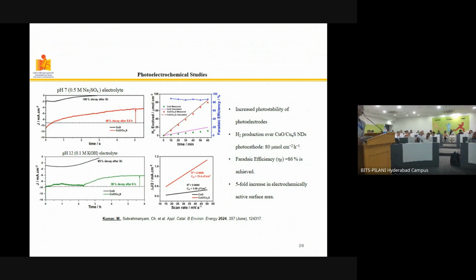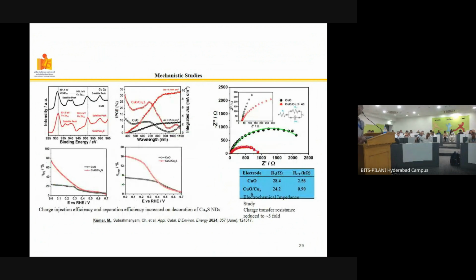And you can also give the hydrogen evolution comparison. You look at the other studies, which also confirm that the Faraday efficiency, if you report, all these things look to be good. Then if you look at the RCT value, the charge transfer resistance, it actually tells that you need to have some kind of a sulfide combination, because we were also thinking about what made copper oxide more active in the presence of copper sulfide.